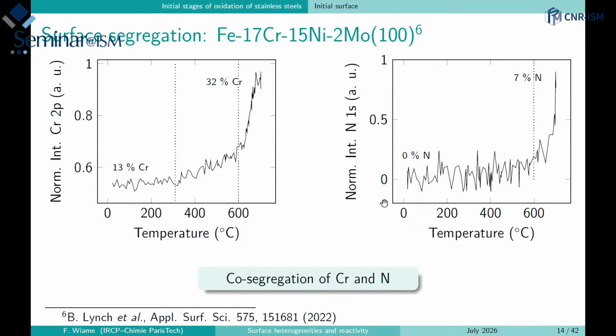And so the first heterogeneity that we have to consider, which is generally forgotten by many corrosionists, is that the surface does not have the same composition as the bulk. And for example, if we are looking at the surface of this material, so this is the 316 material with in the bulk 17% of chromium. If, for example, you are polishing and sputtering your surface, you can see that you have at the beginning a depletion of the chromium. So this is a recording of the chromium 2p signal, which has been recorded in the snapshot mode I explained to you. So we are measuring the full spectrum of chromium while we are increasing the temperature.